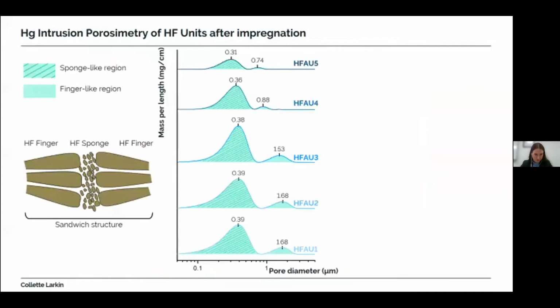So as you can see here, we've got pore size distributions for this finger-like region and the sponge-like region that are present within each of the hollow fibre adsorption units. And since we're depositing our calcium oxide in the finger-like region, I will focus mainly on discussing the impact and what the mercury intrusion porosimetry results show. And they show that as the number of impregnation loops increased, the peak pore size diameter and intensity of the pore size distributions for the finger-like region decreased.